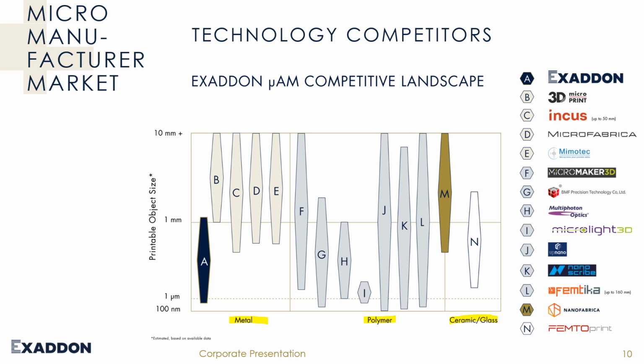When we go to the metal, you see there is only one company which is able to produce parts from below 1 micrometer to a millimeter in size. This is us. The others, they are starting basically above a millimeter and even larger, and they use then powder bed fusions, for example. So you can have metals in larger parts with different technologies, but smaller than 1 millimeter, we are the only one on the market.